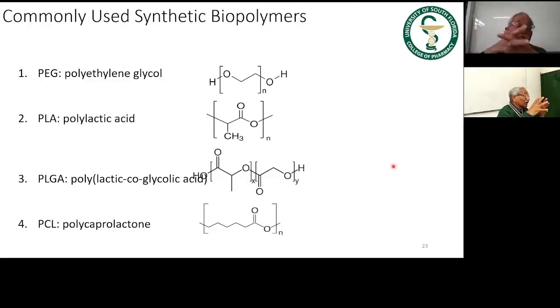So what we are doing is using polymers to build polymeric drug delivery systems so that we can reduce the frequency of injection. Commonly used synthetic biopolymers are polyethylene glycol, polylactic acid, polylactic-co-glycolic acid, and co-block polymers of these combinations. You have to understand one thing: if your drug is highly hydrophobic in nature, you may use polycaprolactone and combine it with polyethylene glycol so that there will be channels to release the drug. Polyethylene glycol is hydrophilic, and polycaprolactone is hydrophobic. So a combination of hydrophilic and hydrophobic polymer will give you release of the drug.